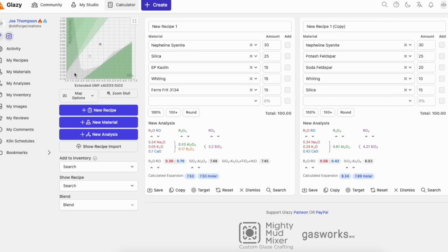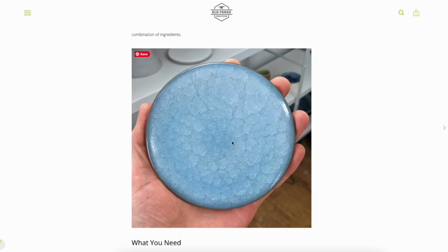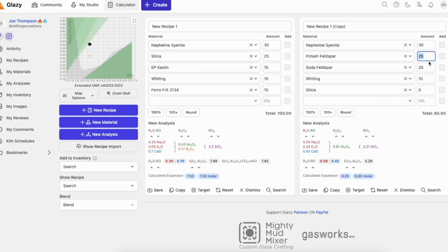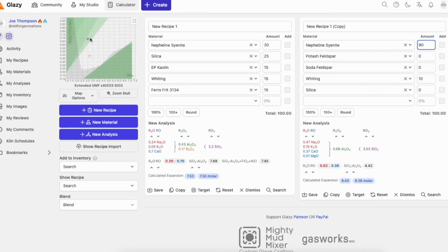Because we've got 75% feldspars, we've actually got quite a lot of glass former and stabilizer. It'd be interesting to see what that does. That recipe there is a snowflake crackle, and you get a snowflake crackle by essentially having that. If you went something like 90%, we've gone high enough in terms of silica and alumina with that recipe that it gave us. It actually possibly might not run, definitely not going to be food safe, but I'm intrigued to see what it does actually do.